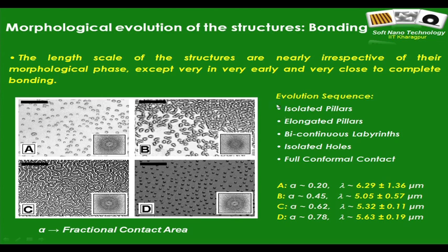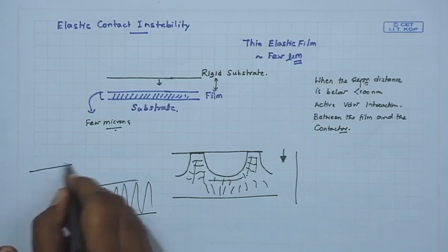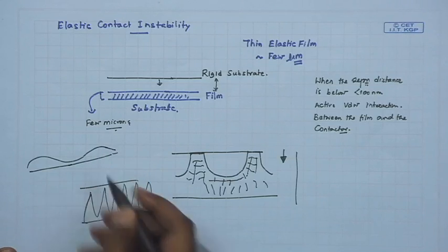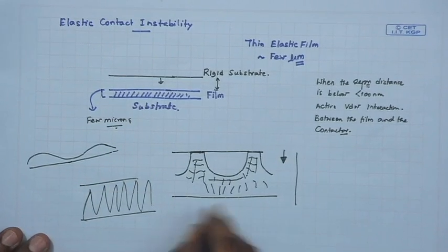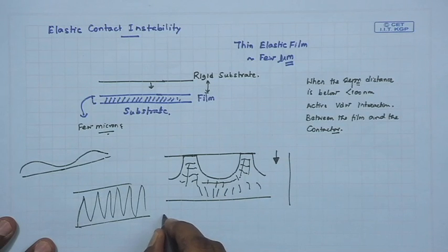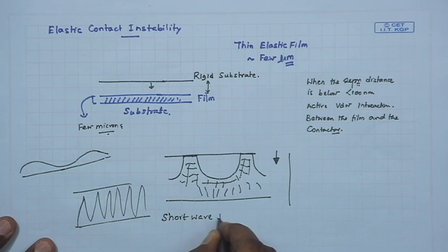And that's why you saw some very closely packed patterns, and that is because as some areas go in contact, the other areas pull down, and that is related to the elastic nature of the film. And this in fact leads to undulations on the surface which are like this, in clear contrast to dewetting, where the wavelengths were much higher, and therefore this form of instability is called the shortwave instability.